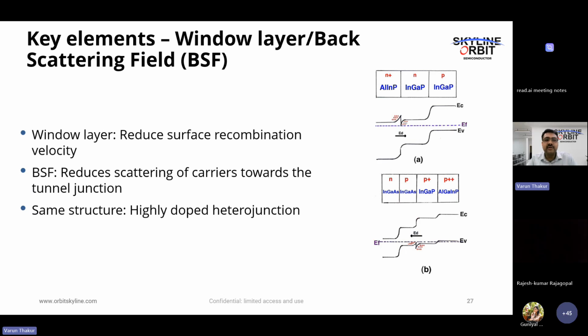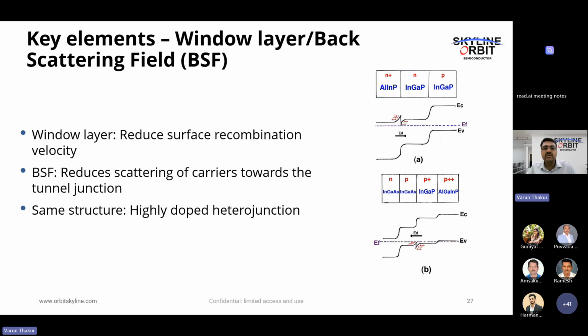So now the second key element is the window layer or back surface field. So as you saw in the slide where I showed this heterojunction solar cell, we have something called a window layer. So the purpose of the window layer is to let in the maximum amount of sunlight, but prevent the carriers from going back. So the same thing happens in the back surface field also. So at the bottom of the solar cell as well, we don't want the charge carriers to go out by any other method except for the circuit, right? So how do we do that? We again employ a highly doped heterojunction, so that prevents the charge carriers. Basically, the highly doped heterojunction repels the charge carriers back into the cell, so that the charge current generation becomes higher, right? So these are the two main elements.